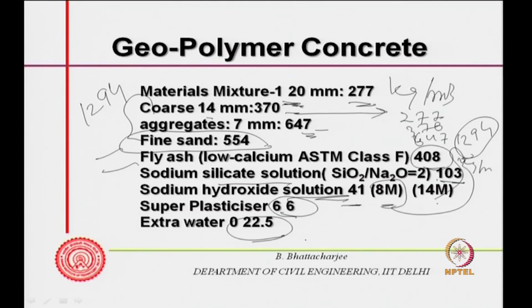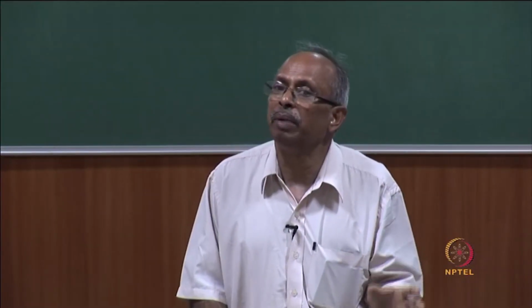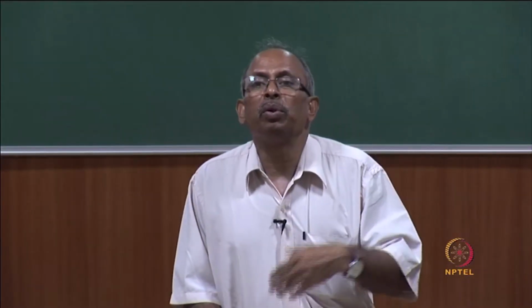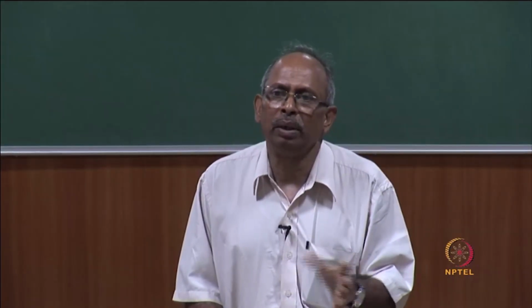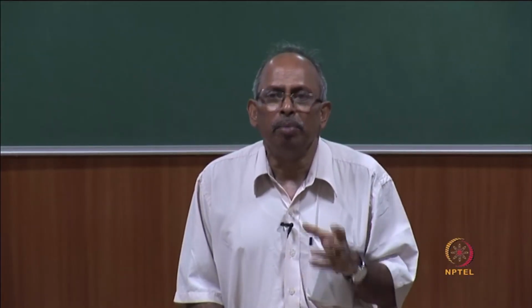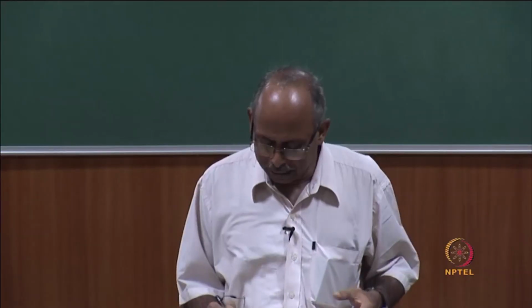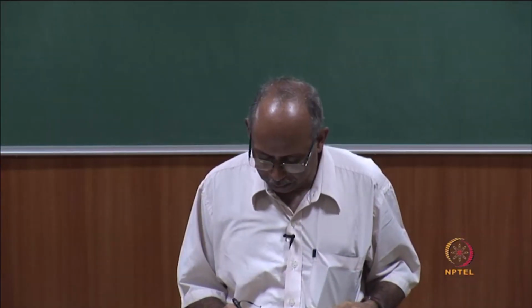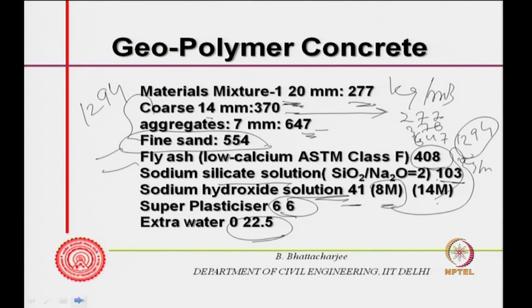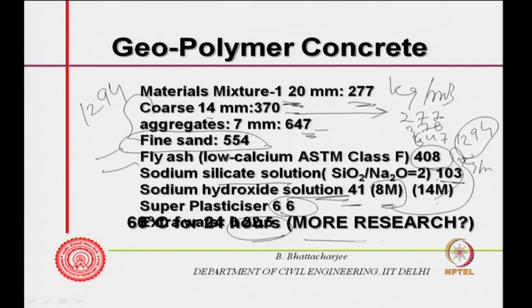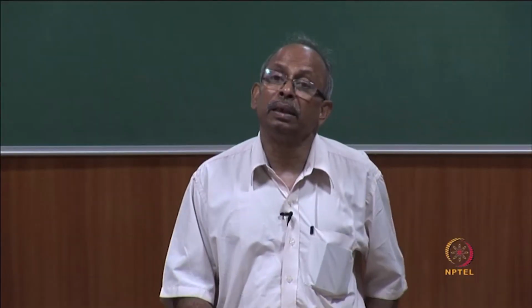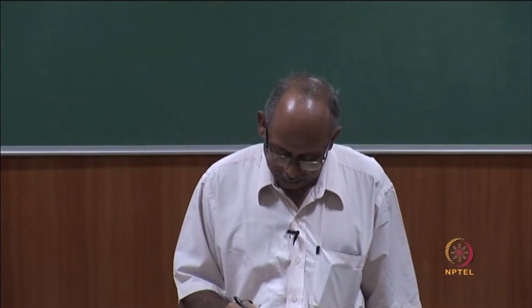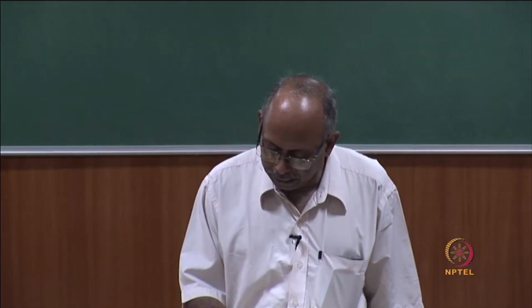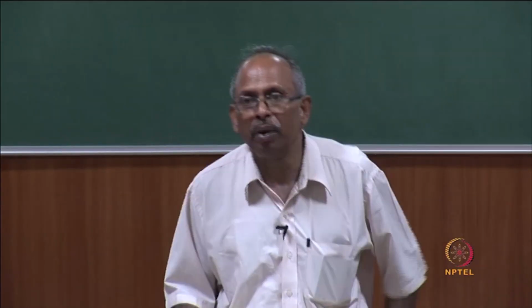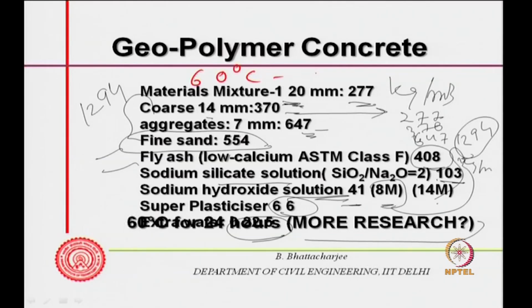So, what are you using? You are using fly ash, sodium silicate, sodium hydroxide, and of course, the rest is like concrete only, and then you make this concrete. The curing temperature is 60 degrees centigrade, that is the only problem that is there. Curing temperature is 60 degrees centigrade, somewhere around that, and that is actually the problem.